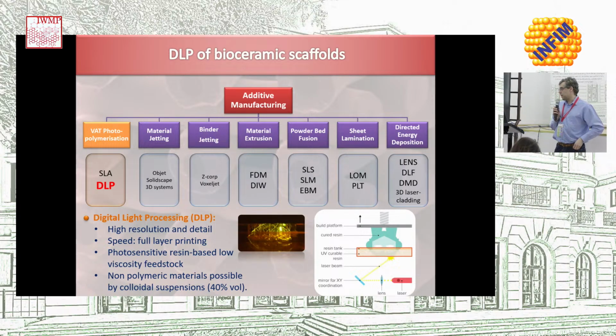So when it comes to additive manufacturing, Antonia has already presented some of the work we did with robocasting, which is a material extrusion additive manufacturing technique. But there are other families of 3D printing. And what I'm going to present today is related to another one, which is called digital light processing, belonging to the family of vat photopolymerization. And this process basically consists of projecting light into a vat, a container with photosensitive resin that will photocure when it's hit by the light, and this produces a full layer in a single step. So the speed for printing should be high, but also because the size of the pixels that we can project with UV projectors is very, very fine, the resolution of these techniques is higher than that of robocasting.